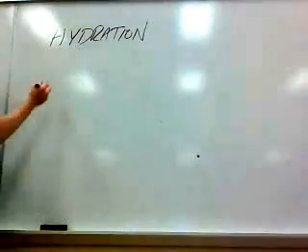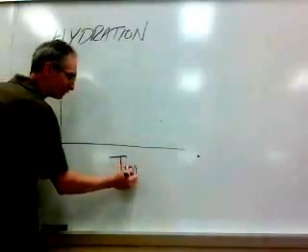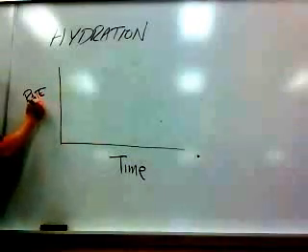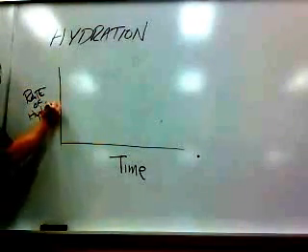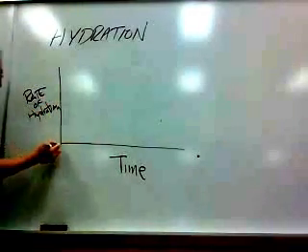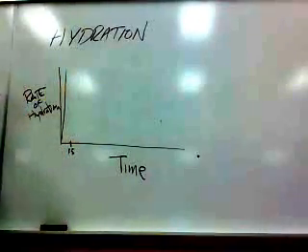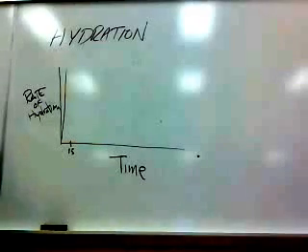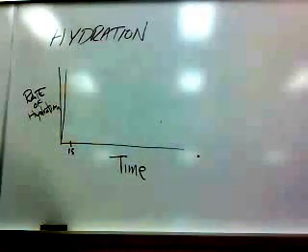But in general, if you were to look at a graph of the rate of hydration, how fast the chemical reaction is actually going, within the first 15 minutes, it goes extremely quickly. Now, in the first 15 minutes, what's hydrating is what they call the aluminate portion, which really doesn't do anything to strength.